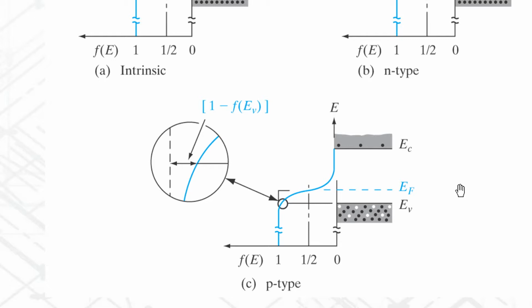The extra 2 electrons also result in extra 2 protons. And so that will create a different boundary condition for the Schrodinger equation, so the solutions to that may change. So when you put a new atom in, there's a lot of things you have to consider. You have to consider the size of the atom, you have to consider how many protons there are, you have to consider how it interacts with the neighboring atoms and whether it will form the tetrahedral bonds that are typical of this kind of lattice.